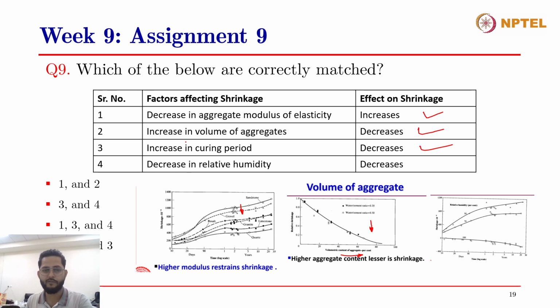And the last one is decrease in relative humidity decreases the shrinkage. This is not correct. As you can see on the third view graph, the three curves show increasing relative humidity, and you can see that as the relative humidity increases, the shrinkage reduces. So this is an inverse relationship. So when there is a decrease in relative humidity, the shrinkage will increase and not decrease. So the correct answer to this question will be 1, 2, and 3.